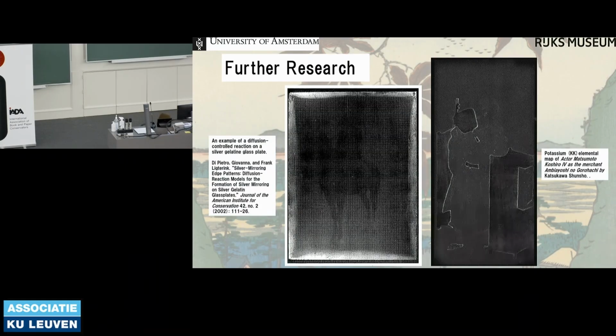So some quick points of further research. First, transmission electron microscopy might be another way to identify particles of lead sulfide that cannot be detected with XRD on my reconstructed samples, and this can be used to further confirm the results of my XANES analysis. And now that I've determined that it seems that the ratio of red lead to impurities significantly affects the amount that it discolors and the final color of the discoloration, I think the next step would be to determine the actual ratio of red lead on historical prints. This could help to identify prints that are at a higher risk for discoloration and to generally determine the quality of artist pigments used at the time.